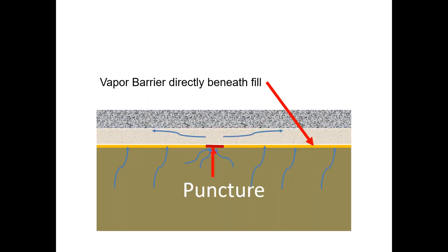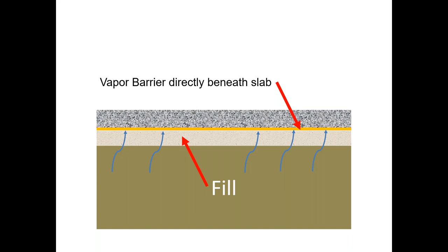Not to mention the fact that, again, if I've got a puncture in the vapor barrier, I can get saturated sand again underneath the concrete. And I can get saturated sand that covers a vast amount of area, versus if there was a puncture just in the vapor barrier directly beneath the slab. If I have a half inch cut in the vapor barrier beneath the slab, the amount of moisture that can get up through there into the concrete is very limited. If I've got it below the sand, the amount of moisture that can get in there is as much as that sand can take. And we know that because of the interstitial spacing in the sand, the vapor and moisture can migrate laterally through the sand. So that's the thought that ACI has regarding that.